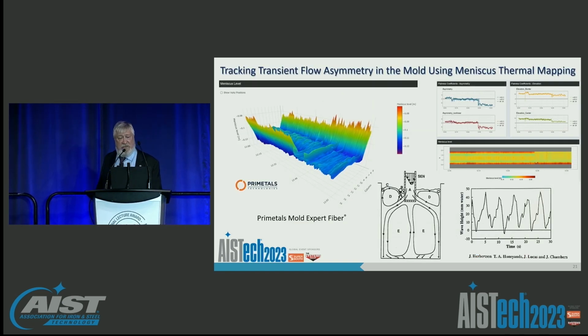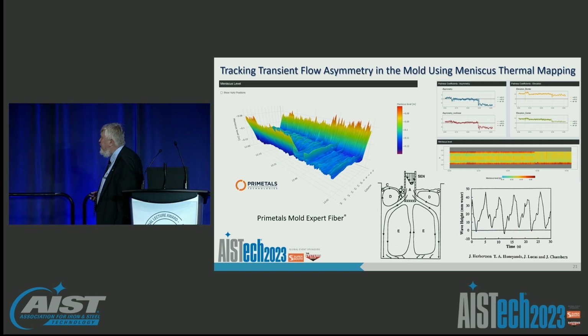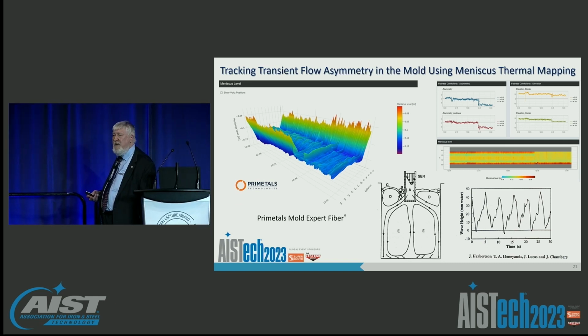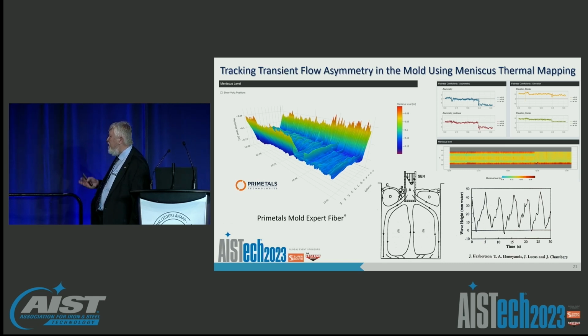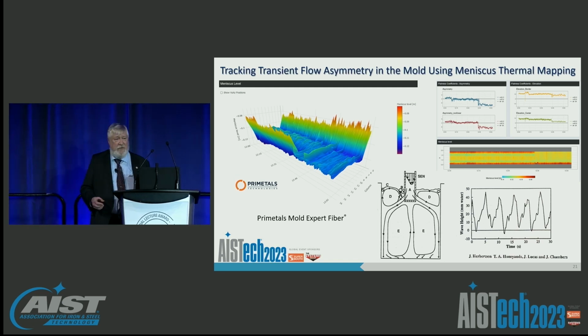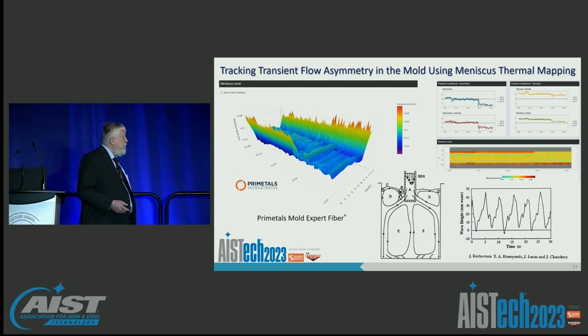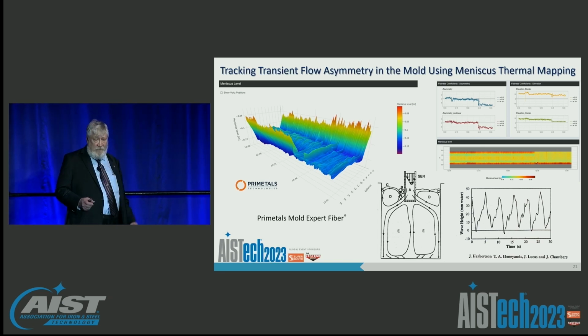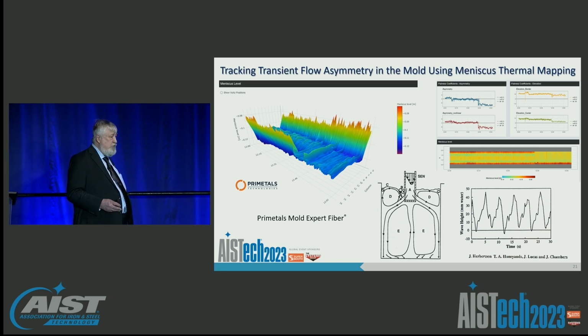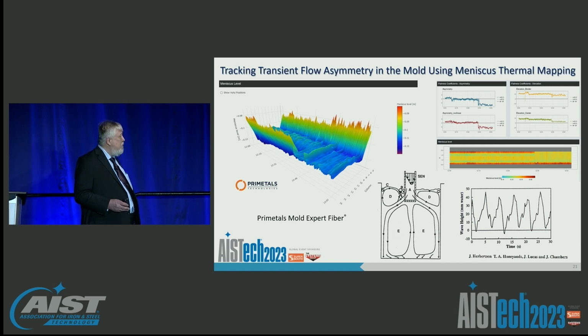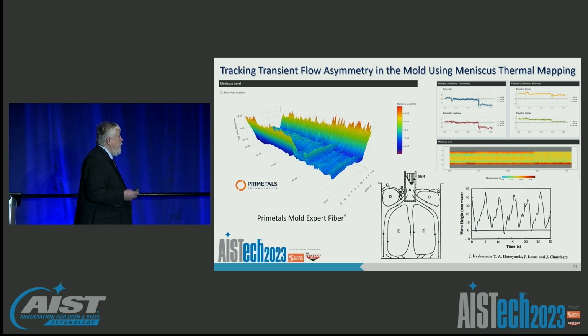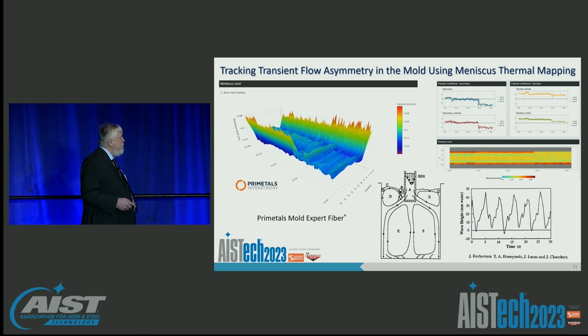So here's just another trace showing one of the common things that is seen in thinner slab, very higher speed casting processes, which is the onset of flow asymmetries. And these can be offset just by flow instability from a submerged entry nozzle. These asymmetries can occur on a regular pattern over a long period of time, sometimes switching on the order of 5 to 15 minutes. They also can be initiated by clogging events that lead to asymmetries in flow. And this just shows a commercial system that's available that is now able to track these things.